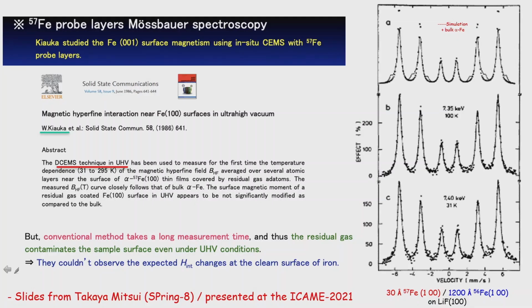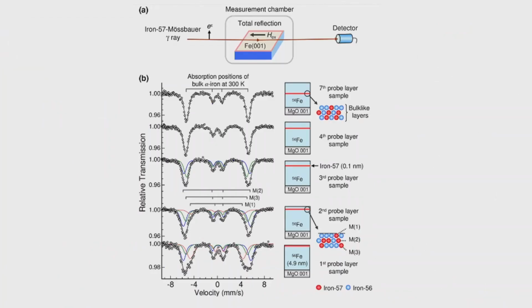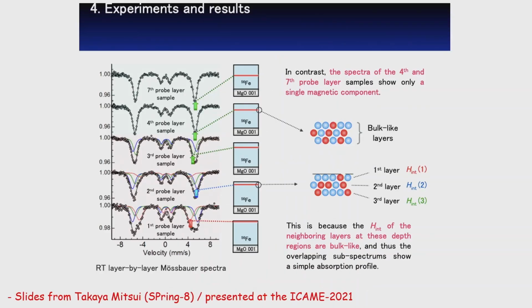But the measurement was done perhaps over a week or weeks, in ultra-high vacuum. That means the surface was contaminated by rest gas, even in ultra-high vacuum. Now what they did at Spring 8, Mitsui did with synchrotron Mossbauer. He was able to grow one monolayer of iron 57 in iron 56, and to see the spectrum from the very surface, or to resolve the Mossbauer spectrum layer by layer, with one monolayer resolution.